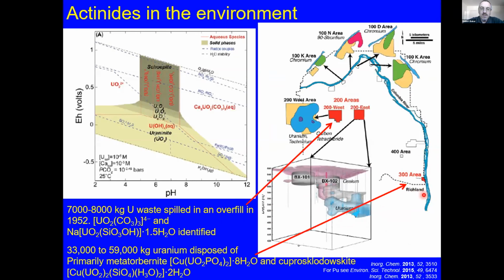In another area, somewhere between 33 and 59,000 kilos of uranium was disposed of over the lifetime of the site. And at some point, somebody decided adding copper was a good idea to control the redox processes. So now the uranium chemistry is dominated by these copper uranyl phosphates and copper uranyl silicates.